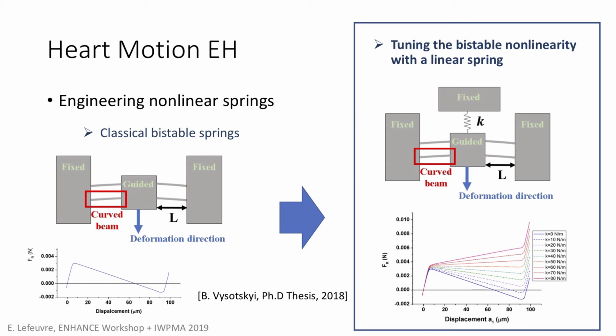And typically we have this shape for the force versus displacement characteristic, and we have two stable points at zero force. Okay, so when you have this kind of force and displacement, this is unstable. So if you push the system here, you will go to this point, and if you push the other side, the system will go to this point. So you have a bistable system basically. So we don't want that.